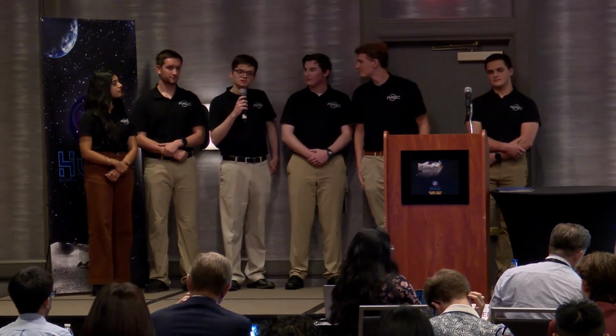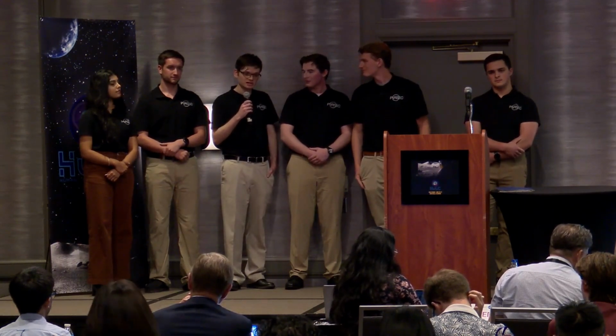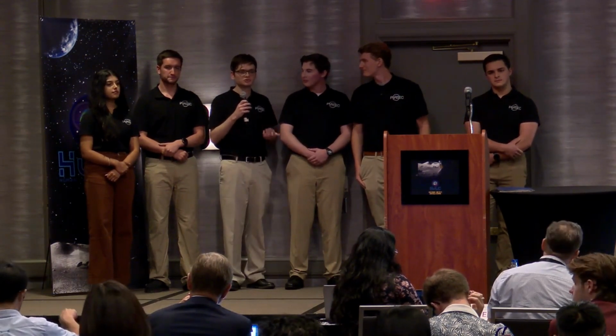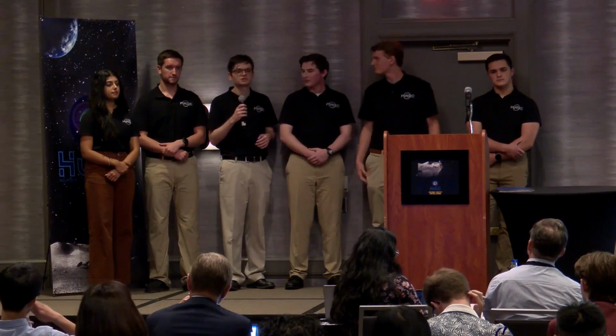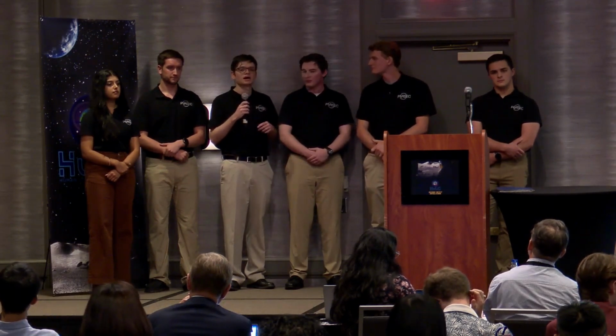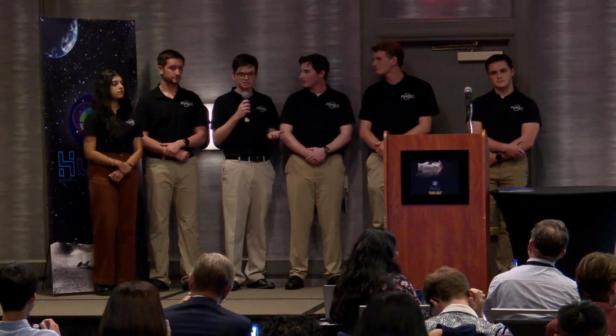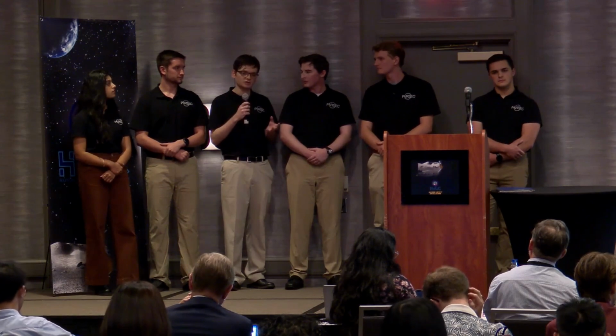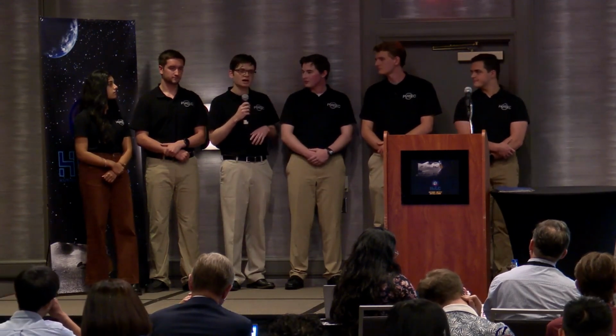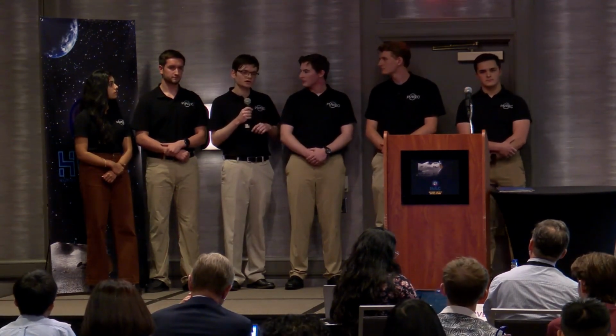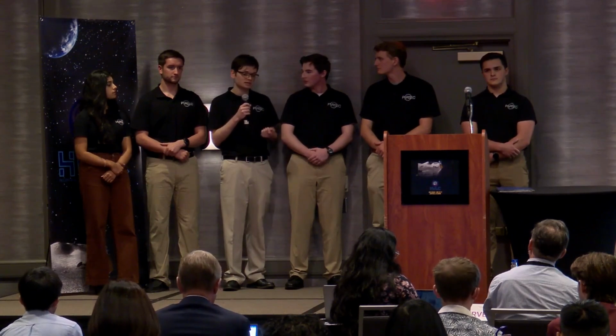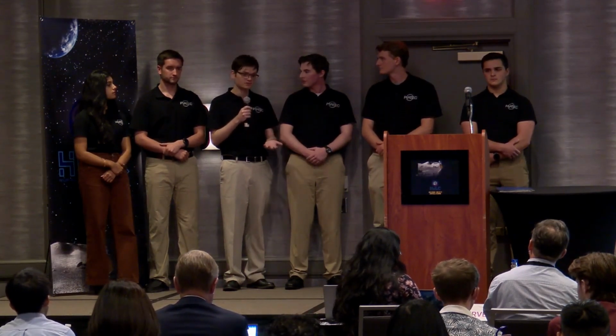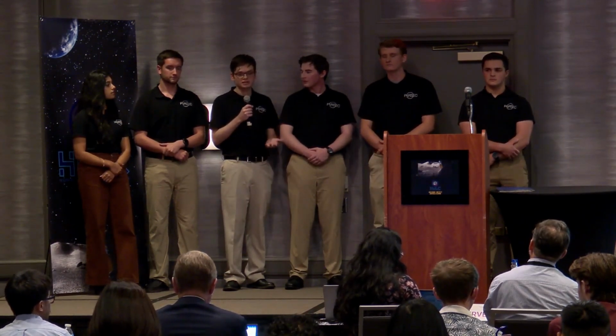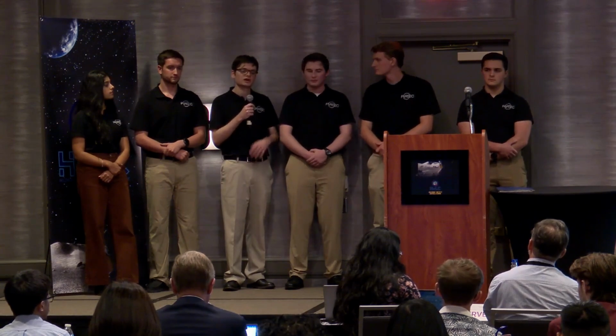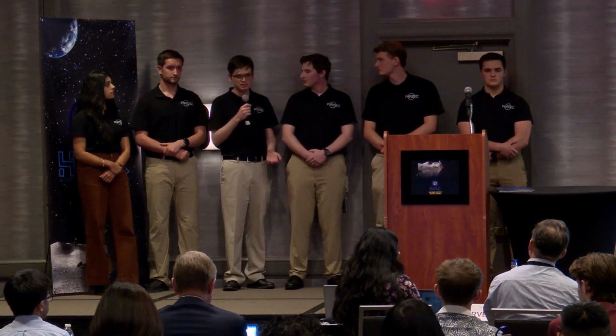What we would like to do is scale up these tests potentially to a lunar yard sort of scale, where we can use much larger motors and then potentially prototype deployment systems, and that way we can get much more accurate at-scale measurements. That 50% that we got was from the testing that we did with the torch. So it is likely that number would change, but we're not entirely sure how it would change until we do the at-scale testing.